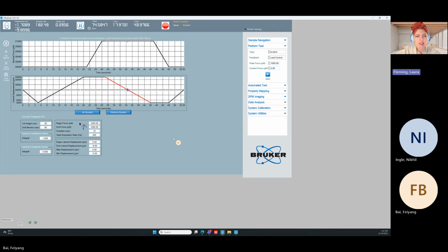So let's go ahead and decrease this force drastically. The problem with scratch training with a Berkovich probe is that we run the risk of blunting your probe. So for the purposes of training, I typically do very, very light scratches to prevent damage. So let's change that peak force to 200 micronewtons. Perfect. And you can see now how this is updated.